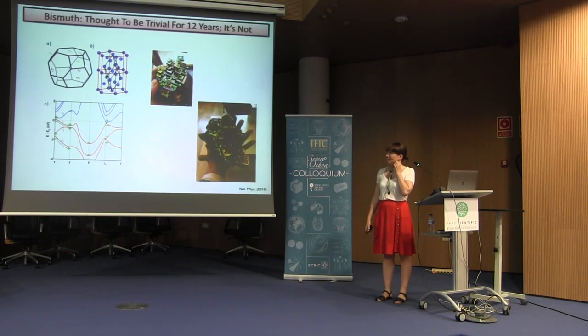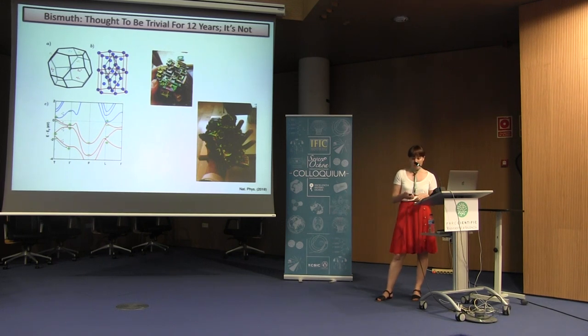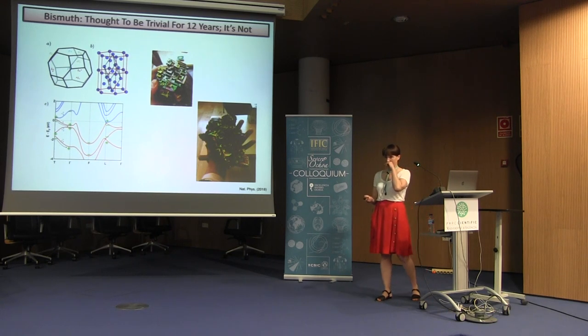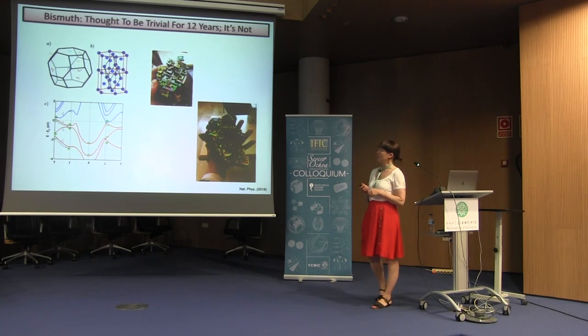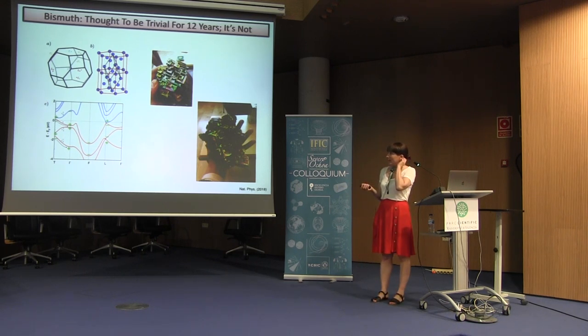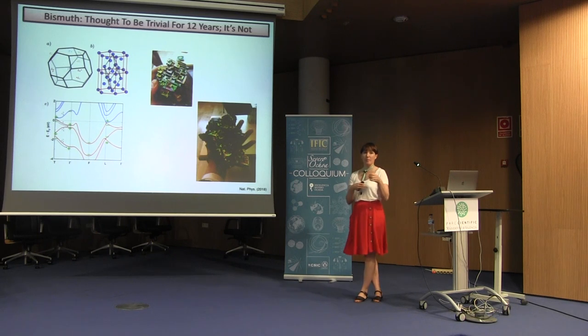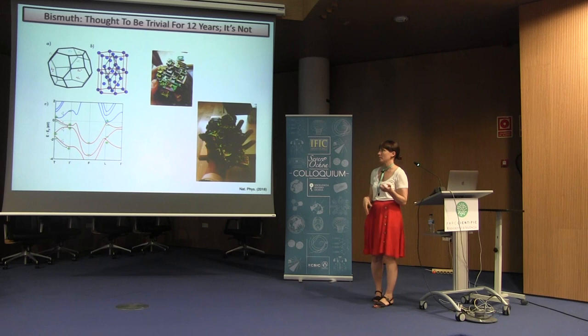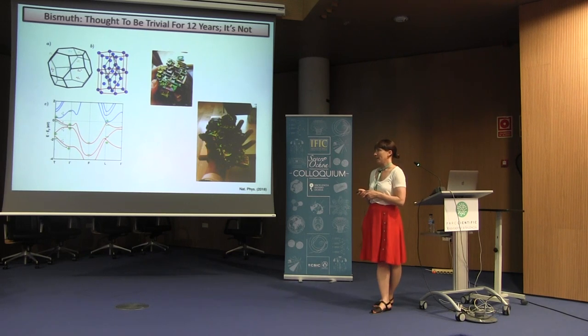So the immediate consequence of this method is that we found that bismuth, a crystal that was thought to be trivial for 12 years, happens to not be trivial. And the reason why people thought it was trivial is because when they look at the surface states, they are gapped, so there is no charge flow at the surface. So by definition, this cannot be topological, because we know that topological materials do not fulfill the atomic limit, the charge has to flow, and in this material it wasn't happening.